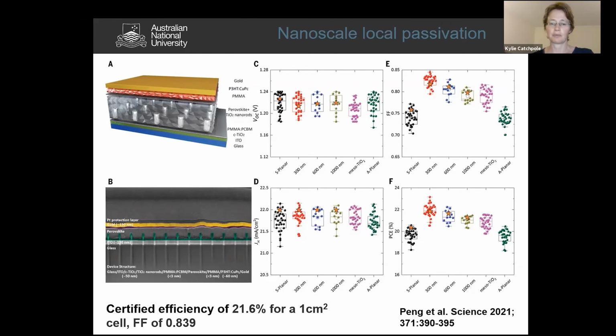So you can see we were able to get very high fill factors overall, a certified efficiency of 21.6% for a 1 squared centimeter cell. So this is a relatively large cell, and that had a fill factor of 0.839.